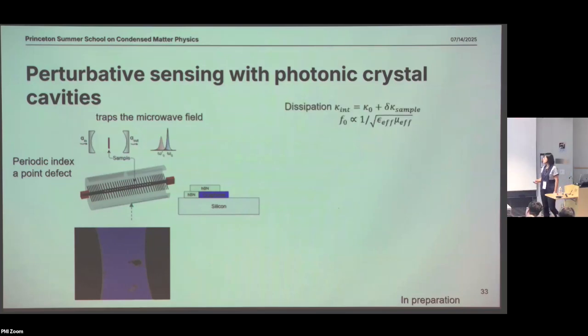So now what we measure is the dissipation or the loss caused by the material, and also the frequency shift of this cavity caused by the material. So the dissipation has two parts. One part is the internal coupling rate, dependent on the geometry of this cavity. But then also the sample will give rise to another part of it. Similarly, the frequency of this whole thing, so this is very similar to the superconducting resonator sensor of MATBG, but it's a different type of cavity.